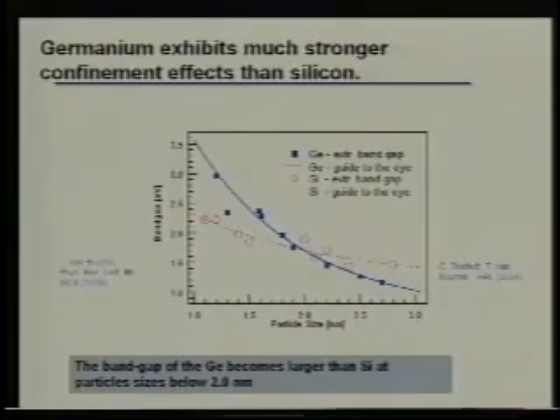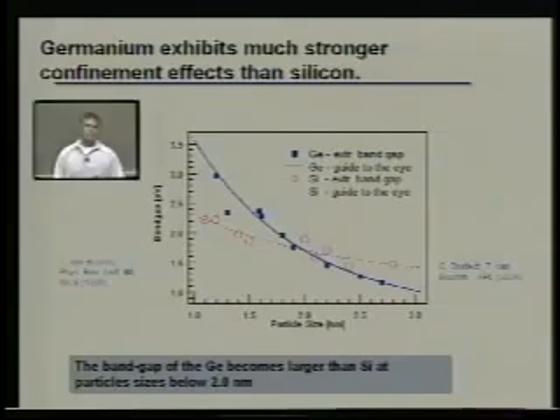Well, if we can make this for silicon, we can also make it for germanium. And the interesting thing here is that at room temperature and in bulk material, the silicon band gap is around 1.1 eV, and the germanium band gap is around 0.7 eV. Yet as we go to nanoparticles at around 2 nanometers, we see that the band gap of the germanium is actually larger than the band gap of the silicon. And here, then, we can use our techniques to do surface-sensitive measurements and bulk-sensitive measurements to actually extrapolate surface features and bulk features.